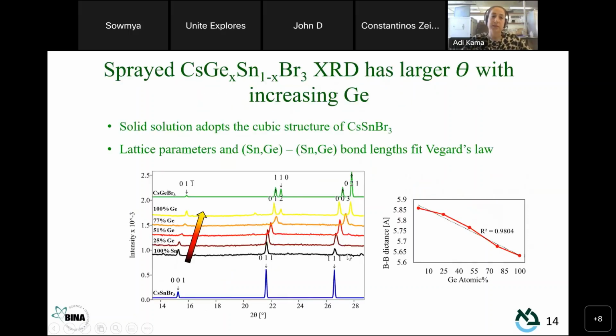From XRD measurements, we see good crystallinity of those films. For the pure tin compound, we see a cubic structure that correlates well with literature, and for the germanium, we see a trigonal structure, and the 3 solid solution compounds in between adopt the cubic structure. We see here a small shift of the 2 theta with increasing germanium, which indicates that the germanium does incorporate in the structure and change the bond length.